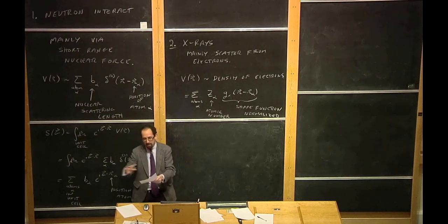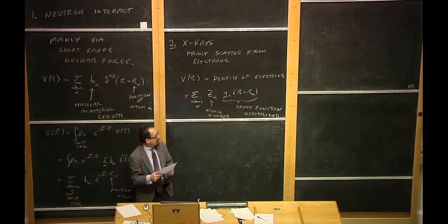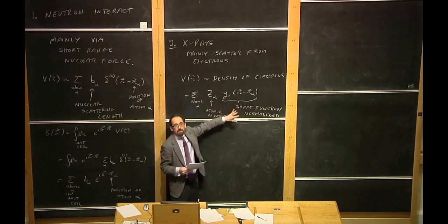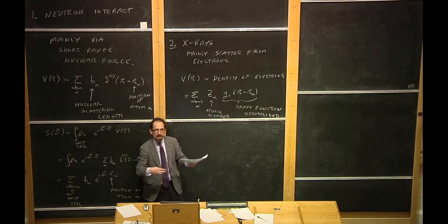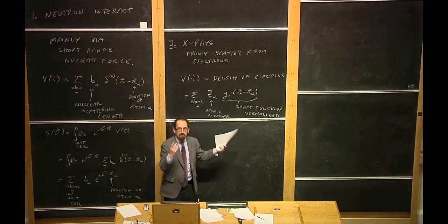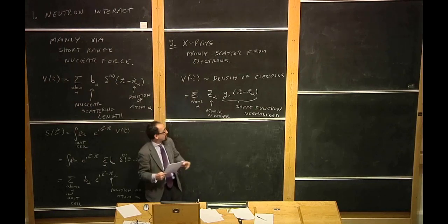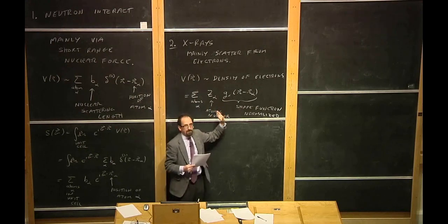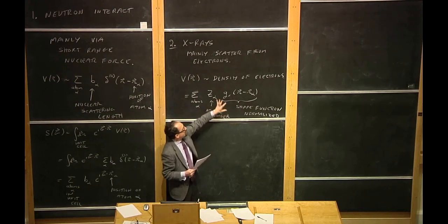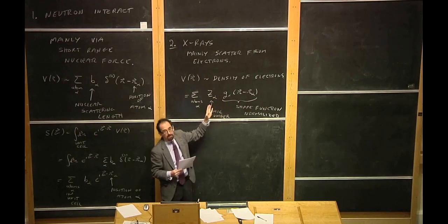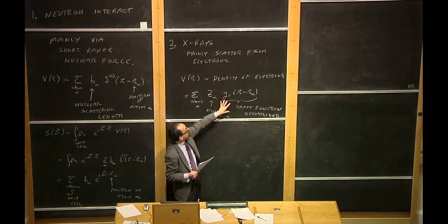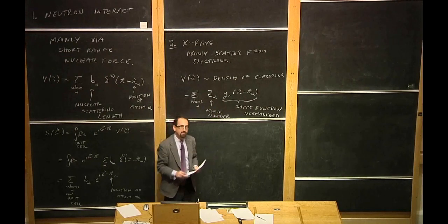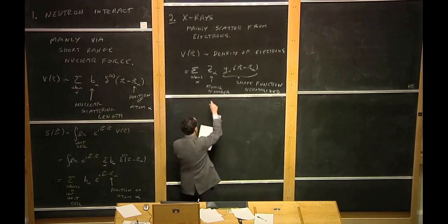If an atom happens to be bonded to one particular type of atom, it will actually distort the electron cloud of the atom a little bit. So the shape will change a little bit, and we've ignored that. And if it's bonded to a different type of atom, its shape will change a little bit in maybe another direction. It will depend on which direction it's bonded and so forth. But to a very good first approximation, this is a fairly good way to describe the shape of the density of electrons in any crystal. You have a shape for a particular type of atom, and you add it up over all atoms, and you ignore the fact that neighboring atoms will distort the shape. Okay? Good? All right.